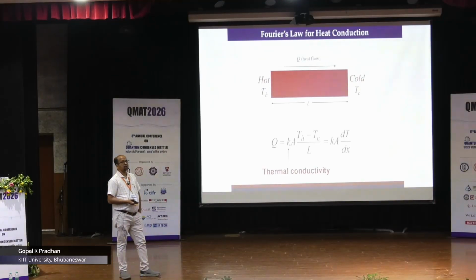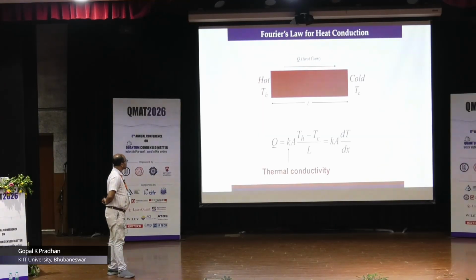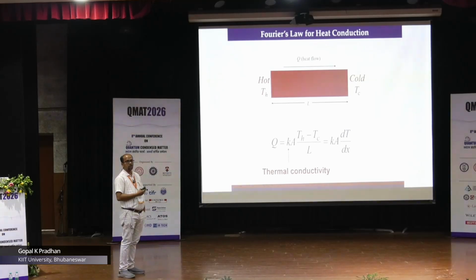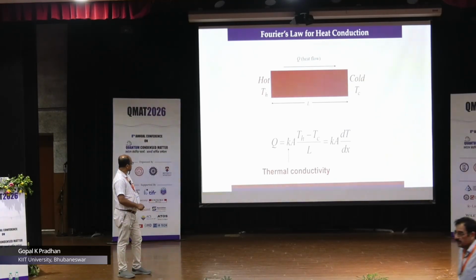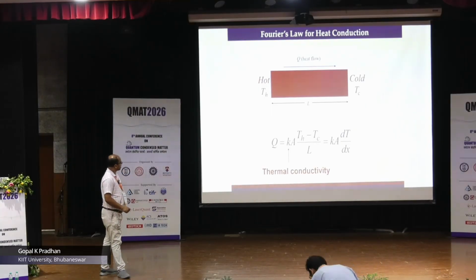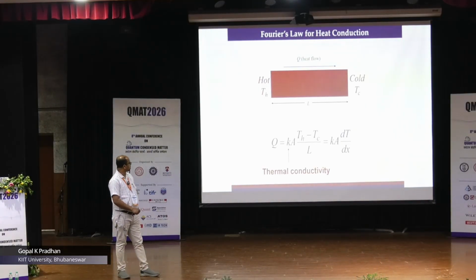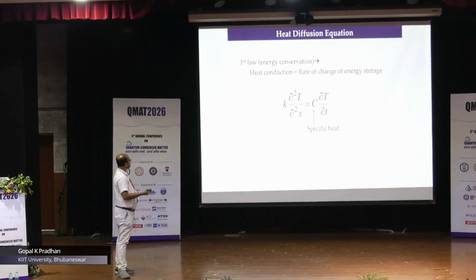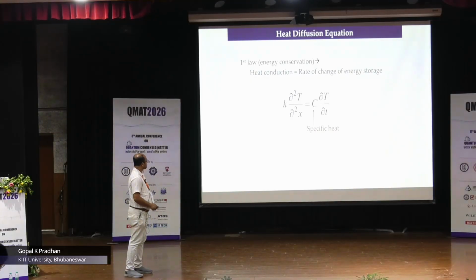If you want to understand how heat is actually transported, you have to understand the thermal conductivity. So you have to understand the Fourier law, where heat always flows from a hot end to a cold end, and this is how the thermal conductivity comes into the picture. The heat is proportional to the gradient of the temperature, and the proportionality constant is the thermal conductivity. And if you want to write down the diffusion equation, this is how it looks. The specific heat appears here, the thermal conductivity appears here, and the heat conduction is essentially the rate of change of the energy that is being stored.